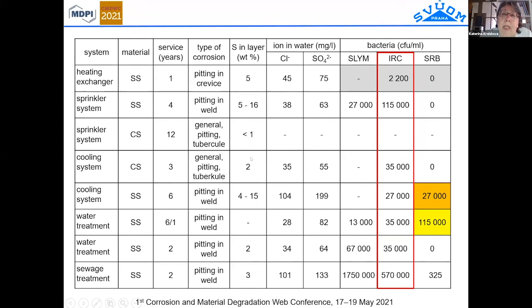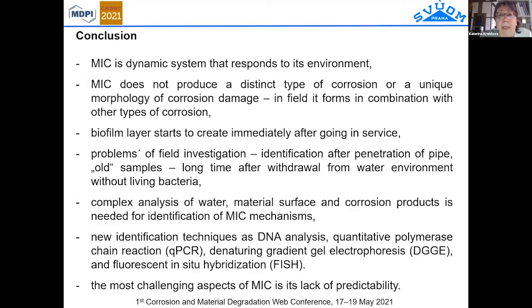Another typical feature is the high content of sulfur in the corrosion products. The water analysis cannot be used as a prediction of this type of corrosion, because it's very different. And what was also very surprising is that in many cases we cannot identify the sulfate reducing bacteria in the water, but in practically all cases we identify the iron reducing bacteria in the water, except again this system, but we have no water sample to be analyzed. So it's very typical for all these cases, and we can conclude that